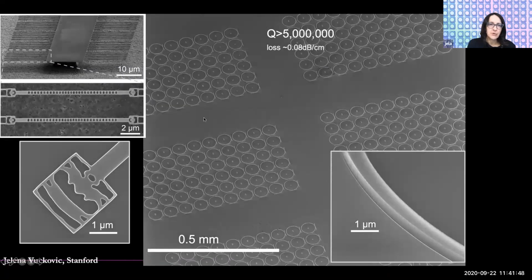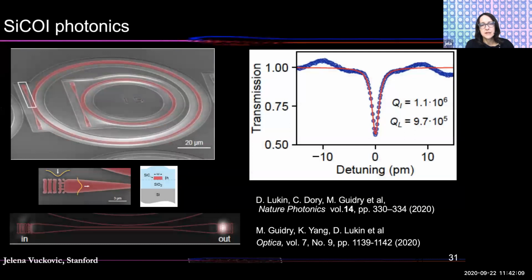So right now, we can make photonics with very high quality. We have very low loss, extremely low loss, smaller than in silicon on insulator. We have quality factors greater than 5 million in the infrared. These are some of the structures we made in silicon carbide, and you see also inverse design couplers. We apply the same approach here. We again measured quality factors, most recently around 5 million. This is a little bit older result where we have Q of about 1 million. This was measured via this inverse design grating coupler and transmission through evanescently coupled waveguide to a ring resonator.